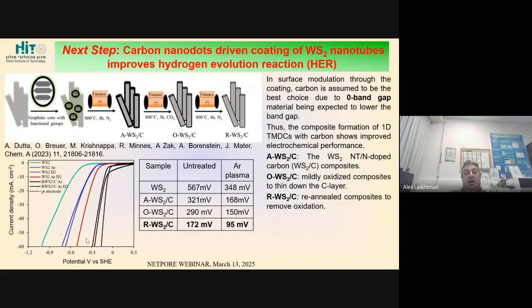And then our solution was, in addition to the plasma, to use carbon nanodot driven coatings of these nanotubes in the following schematic mode. So first we coat the nanotubes with a layer of these carbon nanodots. We chose this type of material because they are zero band gap materials, so we expected that it will generally lower the band gap. WS2 nanotubes, by the way, do not have such a narrow band gap, about 1.9 to 2 eV, unless they are doped.